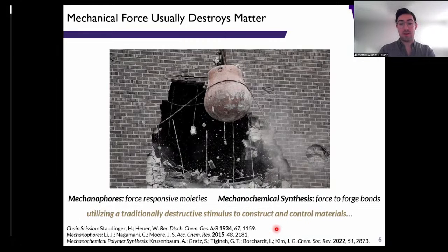So what we're really interested in doing here, as a polymer scientist, is using a traditionally destructive stimulus to construct and control materials, right? With this wrecking ball photo here, we can really think about mechanical force, at least from a first approximation with conventional wisdom, as something that stretches polymer chains out, and this is known from the days of Staudinger almost 100 years ago now. And at some point, you'll end up with these macroscopic radicals that can go on and do further chemistry. But at the end of the day, you're breaking carbon-carbon or carbon-heteroatom bonds along the backbone. And that's not what we want to do here.